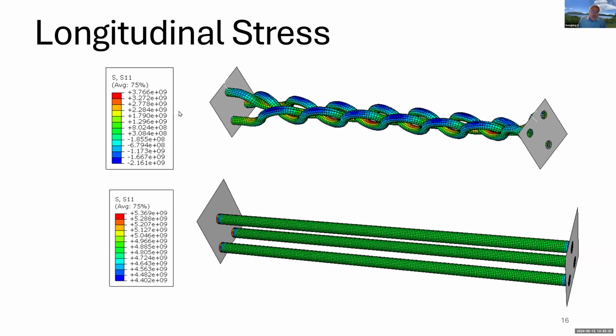The result shows the longitudinal tensile stress comparison. For the braided fibers, everything is the same: same loading, same boundary conditions, same materials. The maximum tensile stress is about 1.5 times lower than for the straight fibers. Again, this is something that meets our expectation.